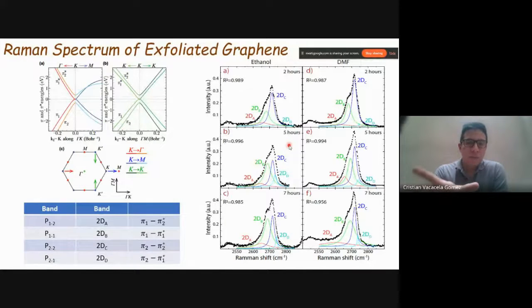But please take caution on this part. I'm not talking about, for example, using liquid exfoliation to get a 2-layer graphene. No, the idea is how the structure of the 2D band in graphite changes when you have few-layer graphene or exfoliated graphene. So if you remember, the 2D band in graphite can only be fitted using 2 Lorentzian functions, but now for few-layer graphene the 2D band structure changes, and now we can fit using 4 Lorentzian functions. And this is another confirmation that we are reducing the number of layers. Of course, we don't have a 2-layer graphene, but our graphene is maybe less than 10 layers. So we are working with few-layer graphene.